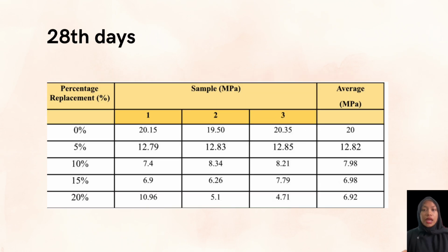So this is the 28 days compression strength test. We can see the average for 0% is 20, and it gets lowest for 5%, which is 12.82. For 10% it is 7.98, for 15% it is 6.98, and for 20% it is 6.92 MPa.